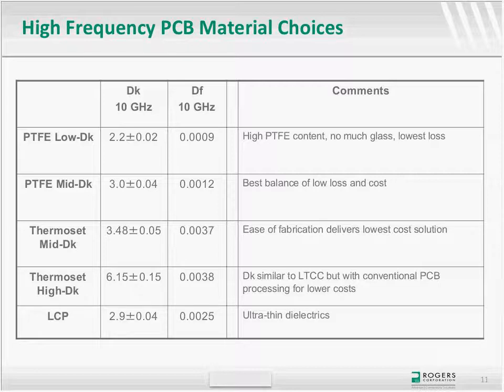When we get to the PTFE mid dielectric constant category, these are materials that typically use PTFE and some kind of ceramic particles. Some of them may have woven glass. Some of them may just be the PTFE and ceramic. Obviously the glass and the ceramic are used in essence for mechanical support. The advantage of the ceramic is that it stabilizes some of the variation in the PTFE when it comes to mechanical and electrical properties against temperature.